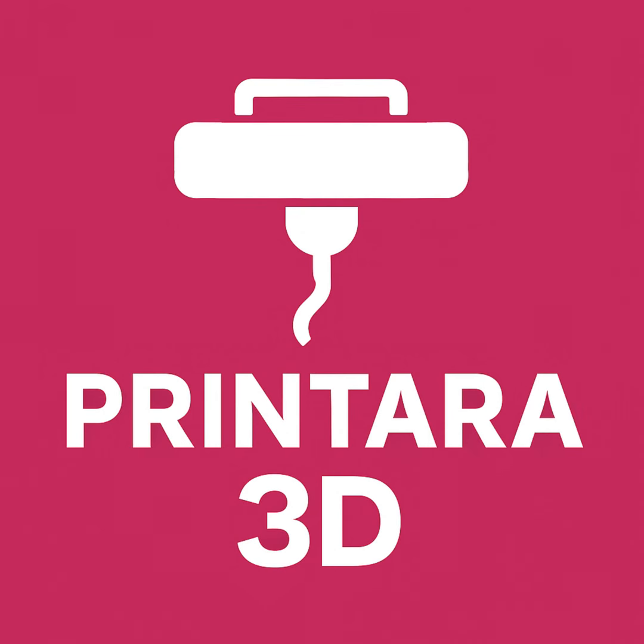It is agonizing. You are printing a large, flat electronics enclosure. 3 hours in, everything looks flawless. Then you hear this tiny, sharp pop sound from inside the printer. That sound is haunting. It is. You look over, and the front left corner of your box has curled up off the bed by 3 millimeters. The dimensional accuracy is ruined. The part is garbage. Why does ABS fight us so aggressively compared to PLA?